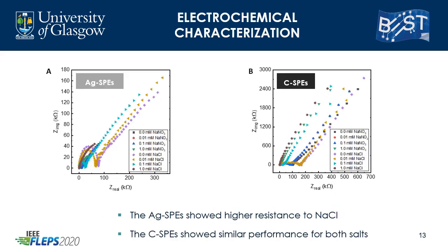Further studies were carried out by increasing the concentration of both salts. Figure A shows that the charge transfer resistance offered by the silver electrode, which corresponds to the semicircle in the medium frequency range, decreased with increasing concentration of salt. However, as compared to the sodium chloride variation, the resistance due to the sodium nitrate is less. This could be due to the influence of the chloride ions in the solution, which reacted with the silver electrode, but further studies are needed to confirm this.